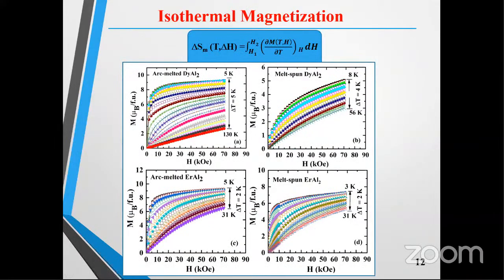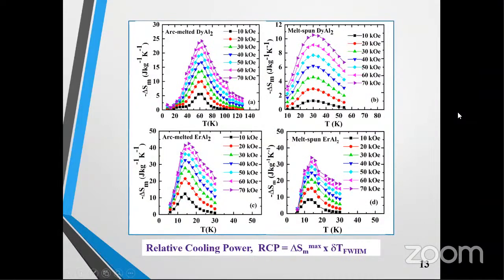And here I have plotted magnetization versus field for different temperature ranges using this thermodynamic Maxwell equation. And from this, I have plotted this negative of change of magnetic entropy versus temperature plot. Here you can see that for arc melted DyAl2 sample and arc melted ErAl2 samples, the transition is sharp at TC and have high value of the negative of delta SM. But for Melt-spun DyAl2 sample, the transition near TC is broad, and this broad transition is good to be a good magnetocaloric material.